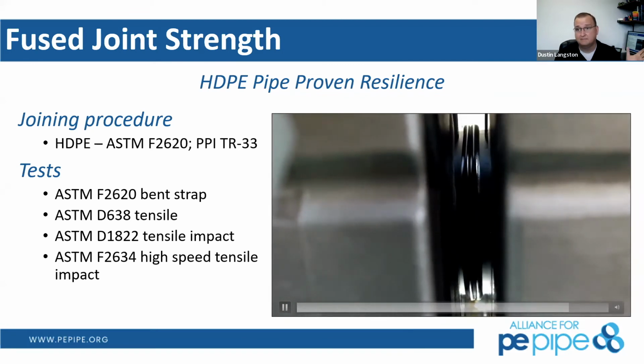We have all the testing and all the fusion standards. So F2620 is the fusion standard. It also includes a test method in there. It's called reverse bend or bent strap, what you can do on pipe walls of 1 inch and thinner. You have D638, which is in-lab tensile testing, tensile impact, high-speed tensile impact. You have a lot of standards out there to test the fusion strength of polyethylene. And again, their claim to fame is the fusion joint is as strong as the pipe itself.